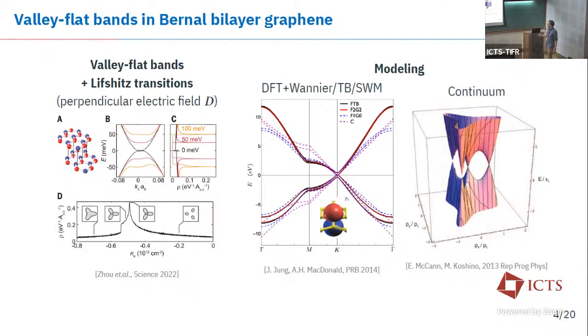And here you see that you have various types of Fermi pockets at certain doping levels that are all controllable via external fields in those samples. I mean, this is the beauty of those 2D materials. And since energy scales are so low and the carrier concentrations are so low, all of this is easily achievable with external electric fields. So, a very highly tunable platform.